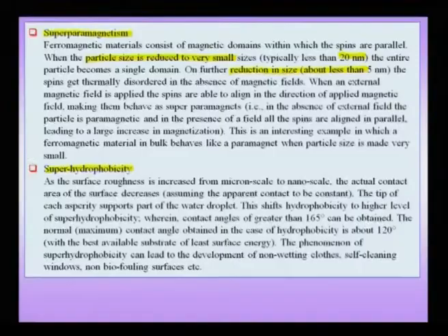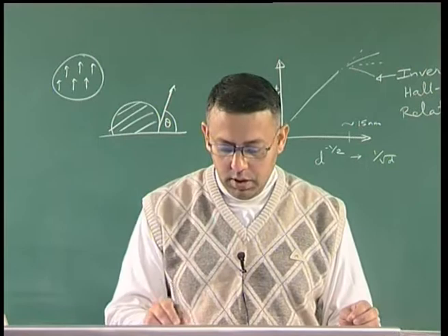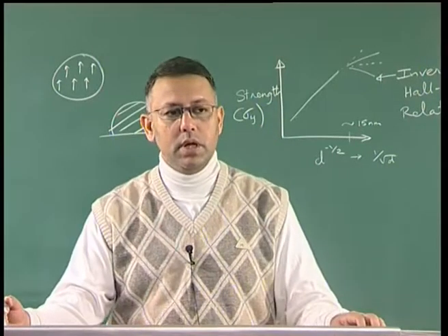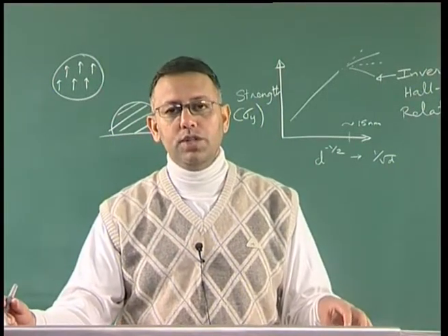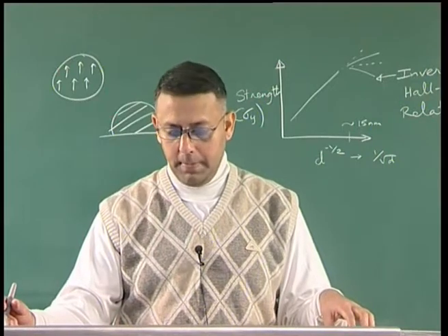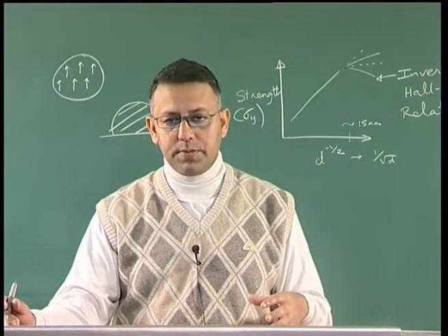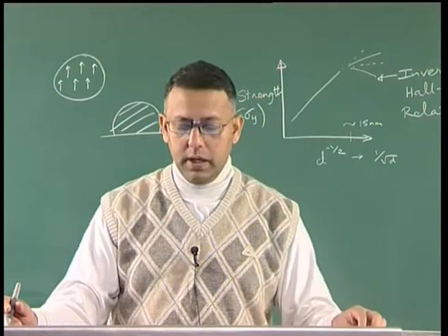So, I measure the contact angle and see what the contact angle is, and I will observe that for normal hydrophobicity, I can get a maximum of 120 degree contact angle. Even 120 degree is possible only when I have the best available substrate with the least surface energy. That means such a substrate does not want to be wetted by water, and at best, by making a very low energy substrate, I can go to about 120 degrees.